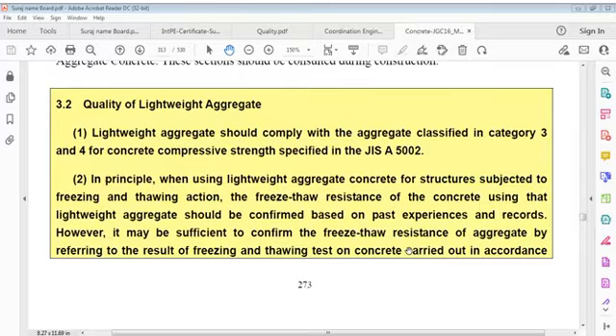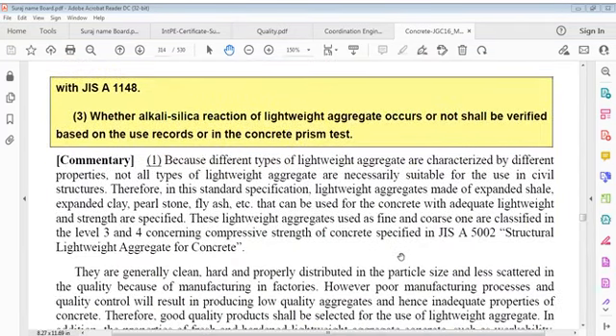In principle, when using lightweight aggregate concrete for structures subject to freezing and thawing action, freeze-thaw resistance of concrete using that lightweight aggregate should be confirmed based on past experience and records. However, it may be sufficient to confirm freeze-thaw resistance of aggregate by referring to results of freezing and thawing tests on concrete. Whether alkali silica reaction of lightweight aggregate occurs or not shall be verified based on use records or in concrete prism tests.